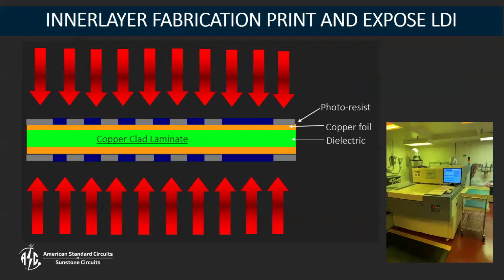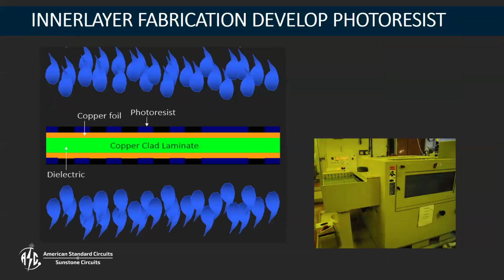So you can see that in this particular design, we have our photoresist, we have our copper foil, we've got voids now in our photoresist where we developed it away. And then what we do is we go through and we develop that resist and remove parts of it. So we're left with the top and bottom. The parts that are in blue is our etch resist, our photoresist. And then the parts that are black on top and bottom are going to be the absence of that, which exposes the copper below it to our etching process.